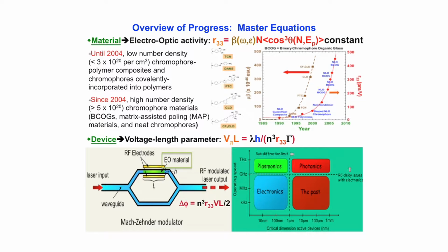The second factor relates to the product of the number density and the order parameter. We have a cosine cubed function because three types of tensors or vectors are involved. And of course, if these are truly non-interacting particles, this cosine cubed function would be independent of number density, and the electro-optic activity would just be the product of these. Since we're using a poling field to induce our acentric order here, in the absence of interaction between particles, that order parameter, called the acentric order parameter, would simply be related to the product of the dipole moment of the chromophore times the strength of the poling field.